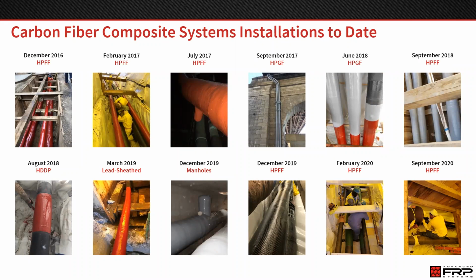We've done a lot of work in the field as well. So you can see starting in 2016, we did some pilot work. We've done work in tunnel systems. We've done high pressure gas filled lines that were at bridge crossings. We've also done spot repairs of horizontal directionally drilled piping systems. We've reinforced lead sheath feeders, and we've done work inside of manholes with huge splice joints and other things on the pipes.